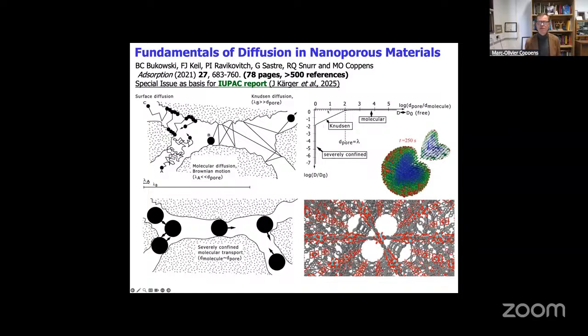But here you might say, well, it's only a factor of 2, 3, 4, right? So if you just put in a tortuosity that is large enough or small enough, you might be able to fit your data. But if then you are going to use that same model under conditions with reaction, or under different conditions, or different molecules that you use, which perhaps see more of the surface or less of the surface, there it comes into play that you really need to include the morphology of the surface. You have probes that are different, say, under your practical application, whether it is in your membrane or your reaction condition, from the one that you would have under the computational condition. So one has to be really careful that you have representative experimentation.